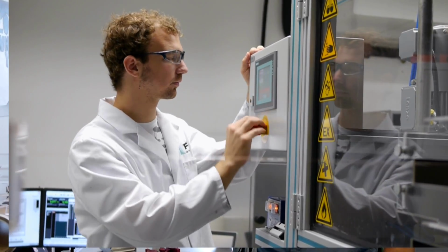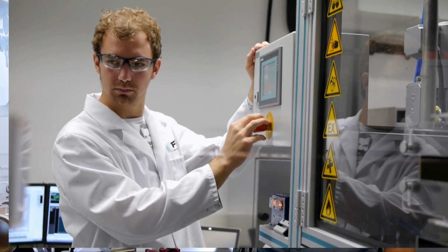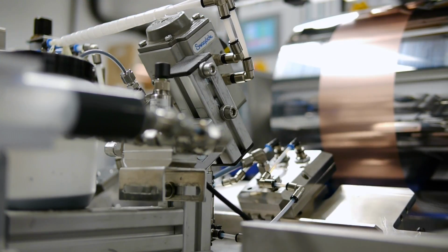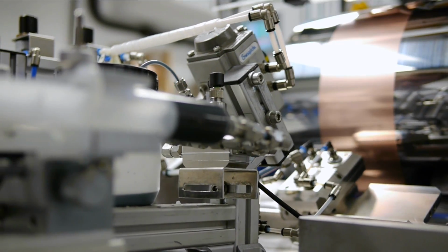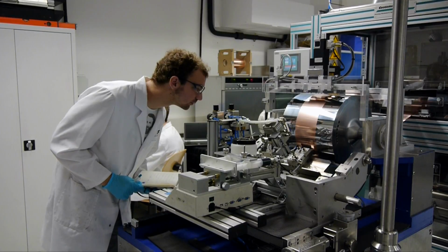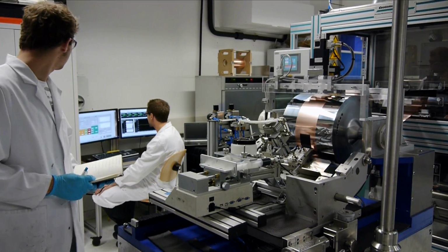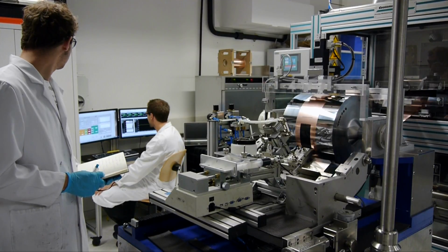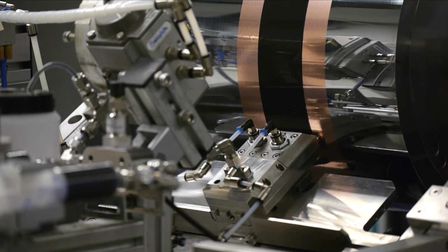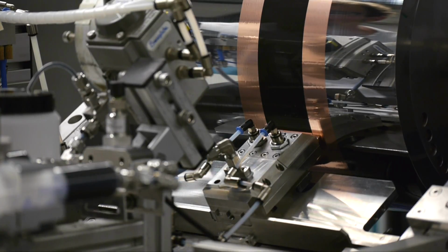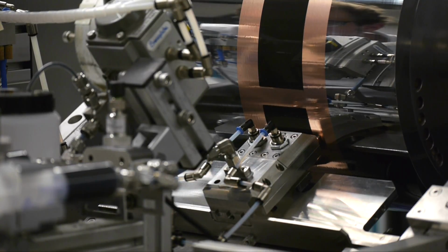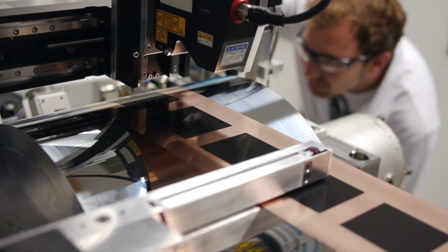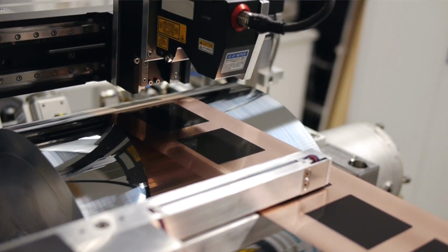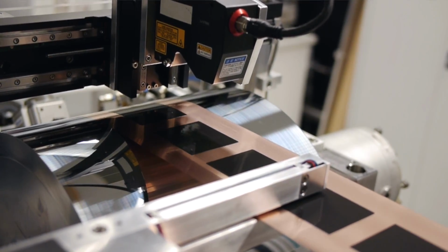To start our coating, we put the bypass valve in direction of the waste pipe. First, we build up a steady state pressure, and then we check our slot die to see if the lips are clean. We go to our pre-adjusted gap and then just switch the bypass valve and start the coating. At the start of the coating, we see there's a starting phase where we have to build up the pressure inside the die. And we first have to put energy in there, which gets stored inside the slurry. So if we reach a steady state pressure also in the die, we then have a stable coating bead where we can coat continuously very smooth and homogeneous films.